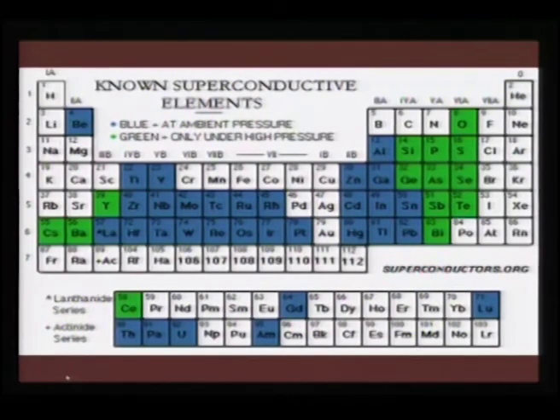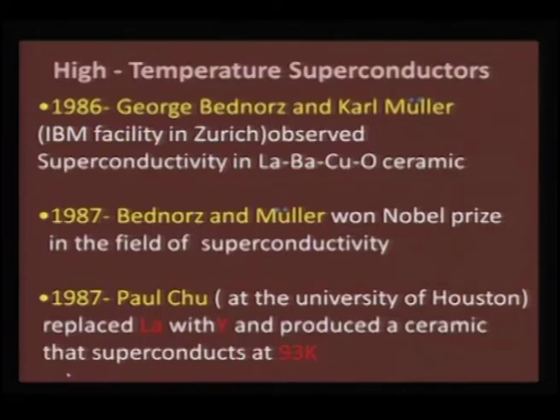Before we look at the major discoveries in this field, I just want to show you that most of the elements in the periodic table do show superconductivity at some temperature, and all the ones marked blue here are superconducting at ambient pressure. But if you go to the non-metallic regions, especially the 4A, 5A and 6A elements, they do show superconductivity at high pressure.